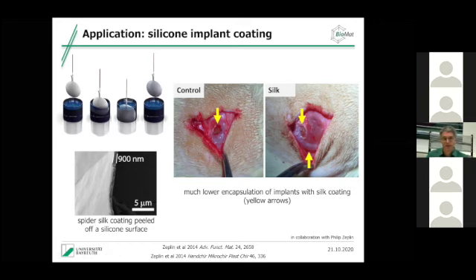Because what might happen is an inflammation, and in about 25% of the breast cancer patients that got a silicone breast implant after their surgery, this implant has to be removed because it causes problems, and this is of course not nice for the patients. In contrast, if you look at the silk-coated implant, you see there's no capsule. There's actually just tissue growing around. You even see vascularization, and this makes this coating very successful.